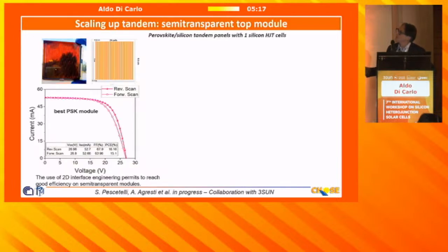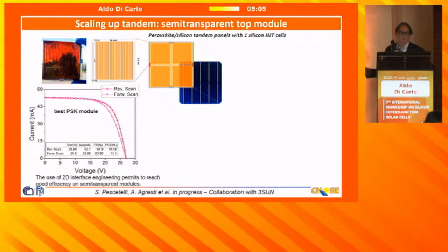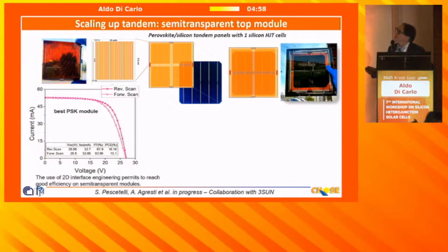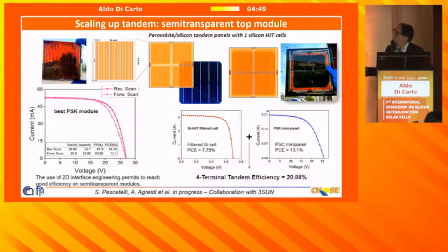Let me show. We were creating semi-transparent modules, something like 10 by 10. And this is the semi-transparent IV characteristic of this module. Then we combined 4 of these modules to cover one silicon solar cell. And this is the final configuration, a 4-terminal configuration. And then you see the final efficiency on this large area was 20.88%. The mini panel was 13.1%. It was not the record that we got before, but the filtered silicon solar cell was 7.78%.